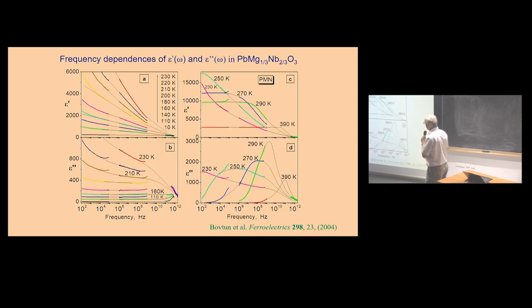and therefore you obtain such broad dielectric dispersion in permittivity and loss. We prove it in this picture. Here are real and imaginary part at high temperature. So at the higher temperatures you see a single narrow peak in microwave range. It means that this polar cluster fluctuates with gigahertz frequencies.